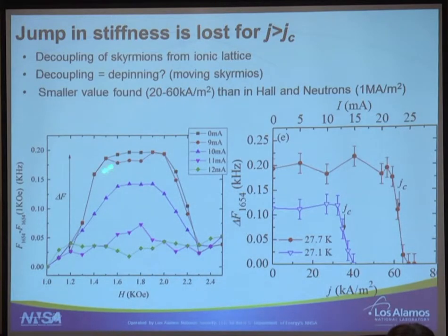Here I'm plotting the results of delta F as a function of current, for 2 different temperatures. So this, within our resolution, is flat until we get to, in this case, 20, 21, 22 milliamps, and in basically 1 milliamp, this goes to 0. And the same happens if you go to a different temperature, but at a much different current.